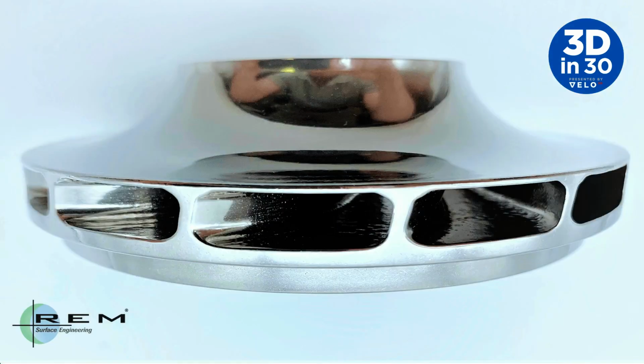And I actually think we've got a nice image of an impeller that was finished. Augustine, maybe you could walk us through it. In the theme of how much you're removing, do you remember how much was removed on this part? I think for this one, we removed around 150 microns, if I remember correctly. This is a Velo 3D component. It was printed without support structures, which is really nice for an impeller like this. They have a lot of internal features, and we were able to flush the chemistry uniformly through those internal cavities and get rid of all those macro defects at the surface. Produce a really cool and beautiful surface.